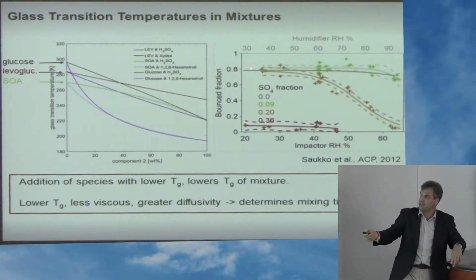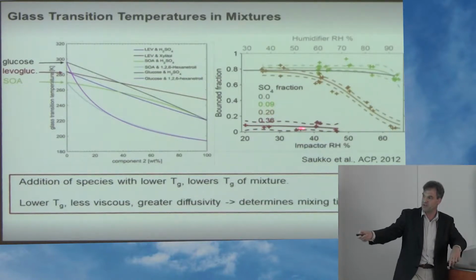So they did that with solid particles, but then they used a secondary organic aerosol and added sulfate. If you have 20% of sulfates in it, as you increase the humidity, you see fewer and fewer particles bounce off. They become more liquid-like, and that changes their reactivity and their interaction with cloud formation. And if you increase it to 36% in this experiment, they're always liquid.